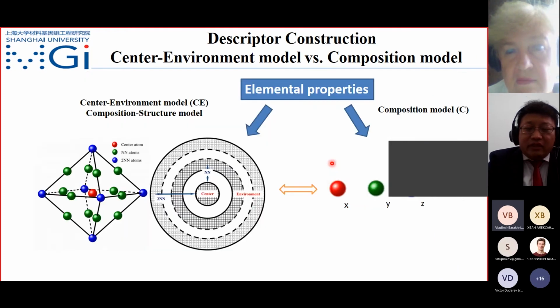Okay, so once we have these elementary properties, we need to build the compound features to describe the system we are interested in. So we propose the so-called center environment model. Traditionally people use the composition model, so basically just the formula of the material, and then they do a linear combination with the molar ratio as the weight to combine these elementary properties to build a compound feature. But in this case, we know the material property is very sensitive to the structure, not just the chemical composition. So in our model, we include the structure information into the features.